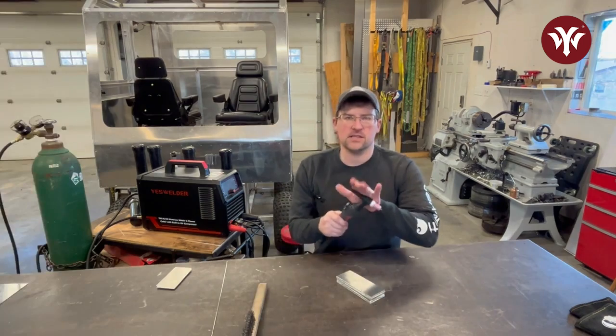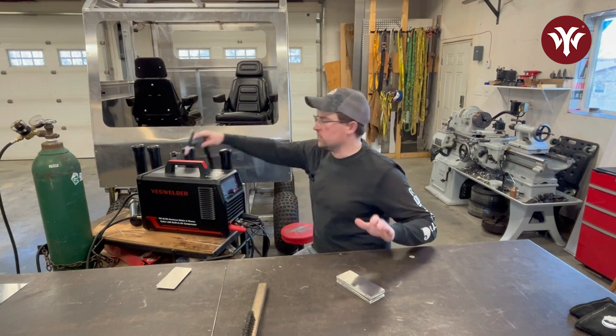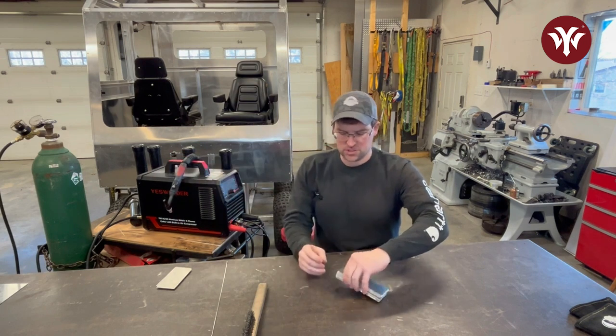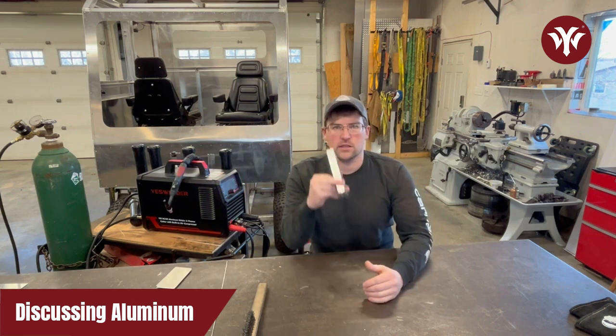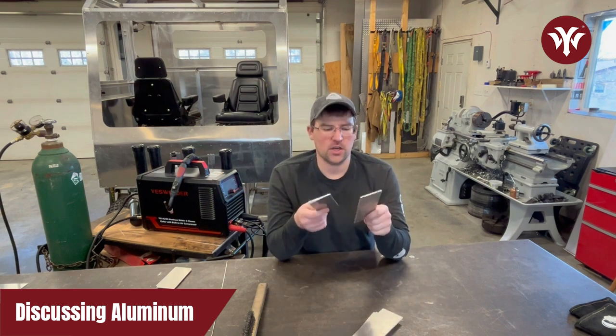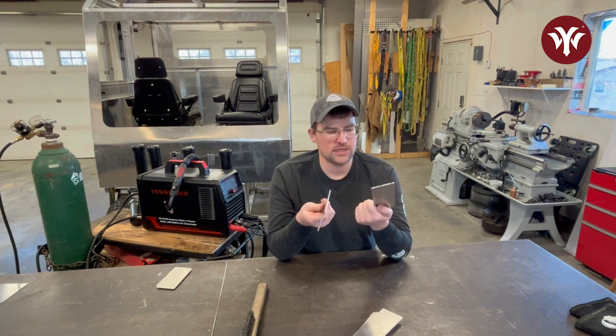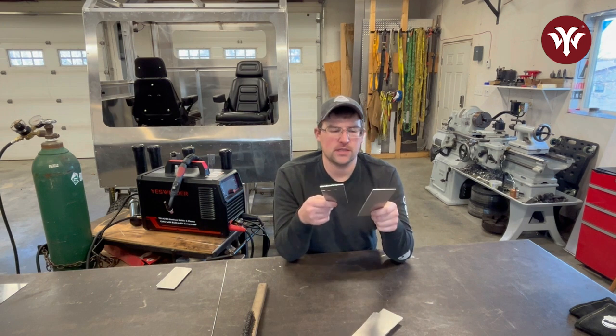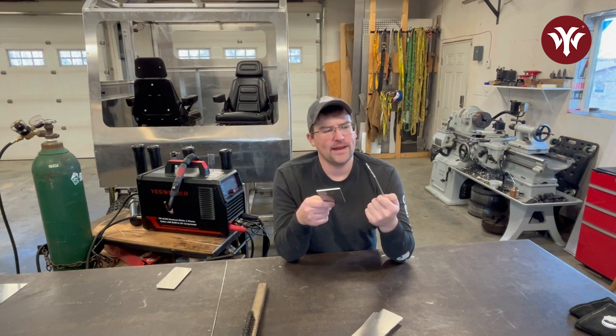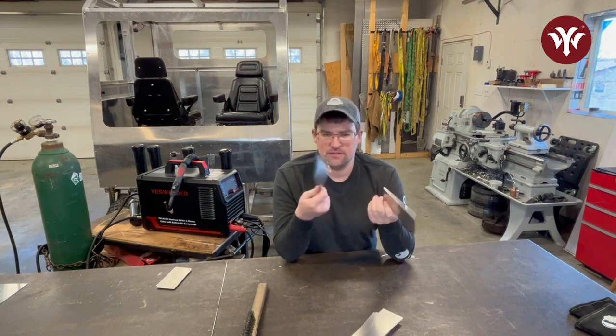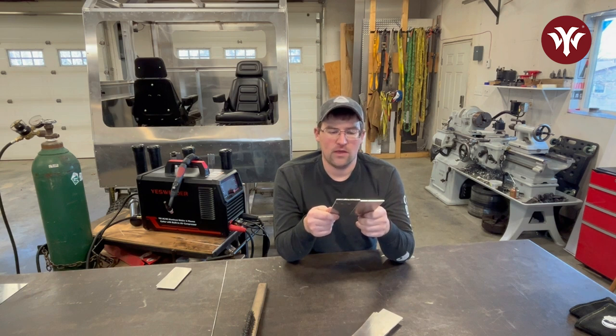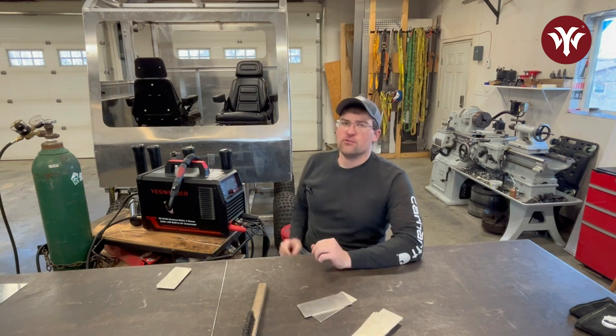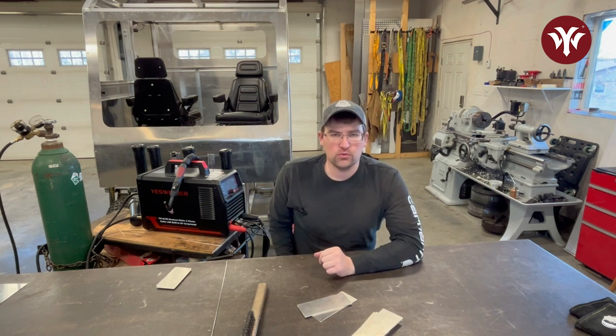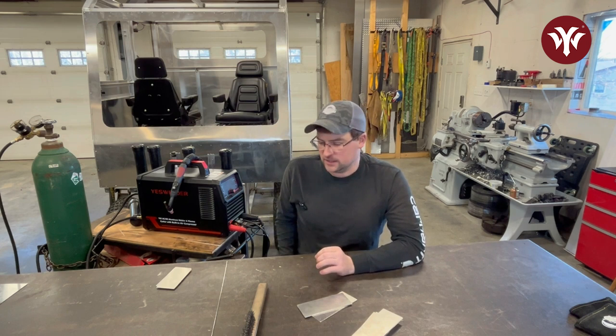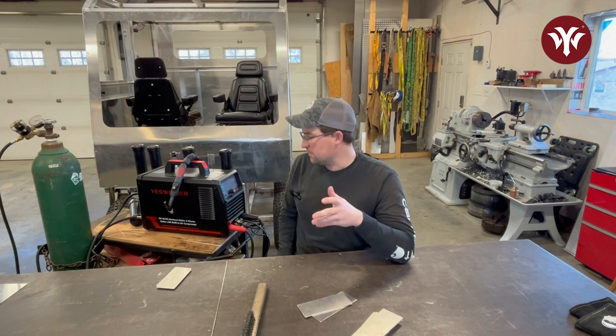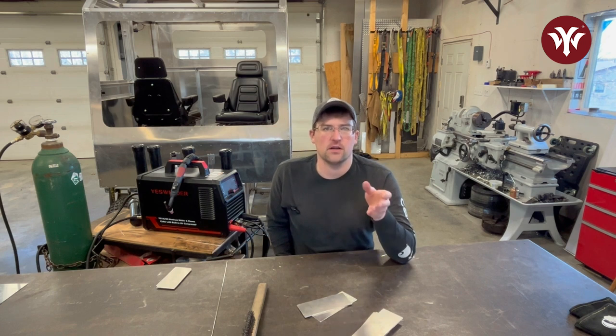Now that we've covered the basics of getting your torch set up for AC TIG welding, which didn't take too much, it's not that much different, let's talk about the base metal, the aluminum itself. Okay, so let's talk about the base metal, the aluminum we're going to be using today. I have cut up a bunch of coupons of 5052 1/8 plate aluminum, or sheet, whatever you want to call it. And with that, we are going to be using a 5356 filler rod. A good rule of thumb with filler rod selection for diameters is you pretty much can choose a filler rod with a similar diameter to your tungsten.